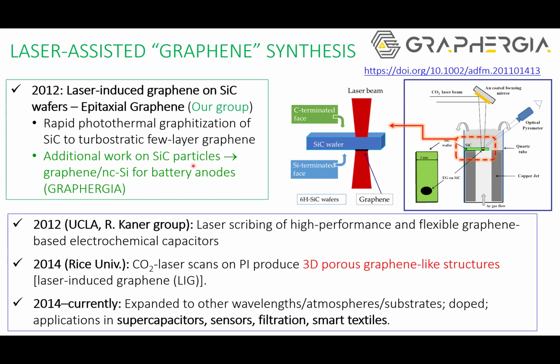And later we also worked with other forms of silicon carbide, for example, different particles from nano to micro sized. And we have managed to decompose this material to its components, graphene scaffolds decorated by silicon nanoparticles. And this is the basis, let's say, that later we used and we are currently using in GRAPHERGIA for producing nanocrystalline silicon decorated graphene-like particles.